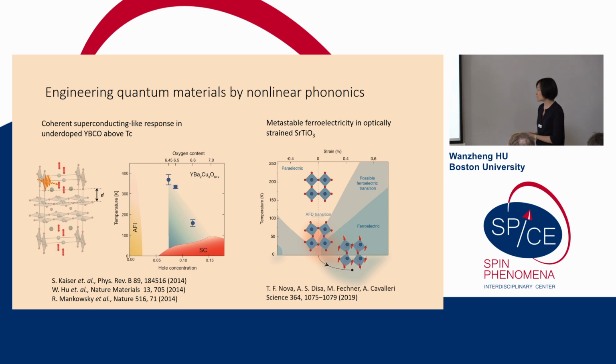The second example is the pioneering work by Tommaso and Ankit, who chose STO and used an intense mid-infrared pulse to drive the highest energy IR active mode. Then they saw a very long-lived ferroelectric state emerge, although the mid-IR pulse had already passed, so the system still remained in the ferroelectric phase.